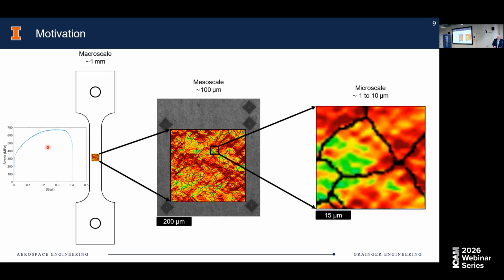Let me animate one more. What I would think of as microscale is a grain level scale, which in the materials I'm going to deal with today is typically of the order of 10 microns, tens of microns perhaps, right? And in between is what I think of as mesoscale, a scale in which the collective response of many grains becomes important. People have studied this for quite some time, and we see various patterns developing. You can almost see it here, right? These bands of strain. Mesoscale is one of the most difficult areas to analyze, right?